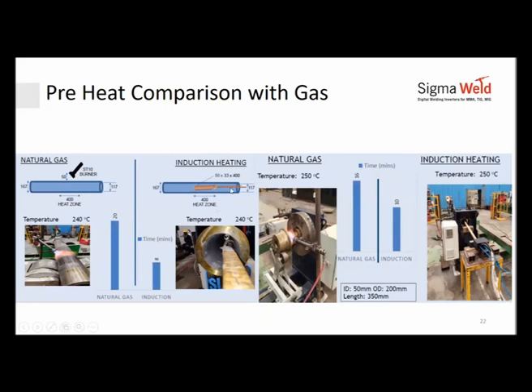However, in induction, we inserted the coil on the inside. And while the coil, this is the inductive coil, the job is still rotating. While the coil is placed inside the heating zone of 400 mm, you are able to achieve the same job in 8 minutes. Now, while this is happening here, the operator cannot approach nearby because you can see the heat around. Here, the operator has no difficulties monitoring the temperature from the top or inside.